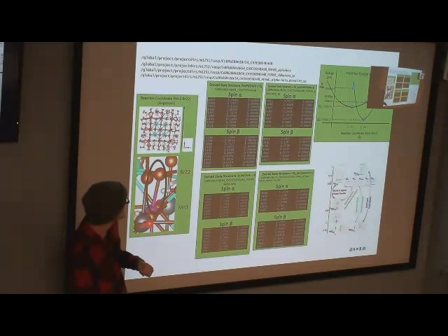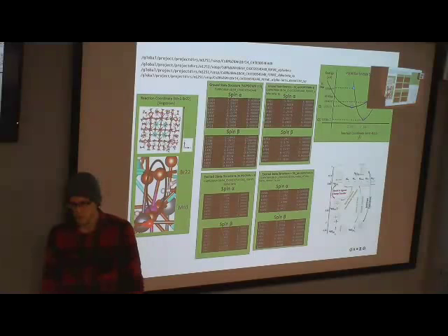And then Aaron, what's the total count of electrons? Is it even or odd? Odd. Yeah, it's odd, I believe. 2809. So what is the value of n up down if you do not constrain it? What is the difference between the number of alpha and beta electrons if you do not apply any constraint? I think it normally takes the high spin configuration, but without specifying n up down. Is that what you're getting at?